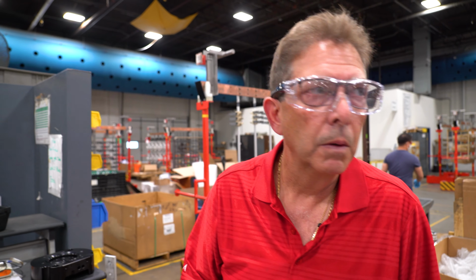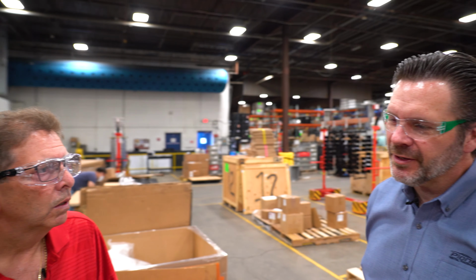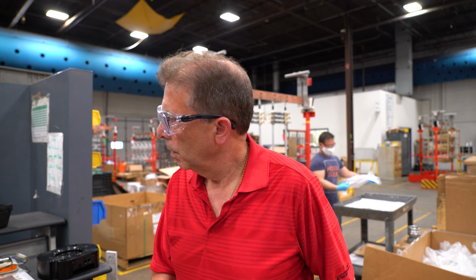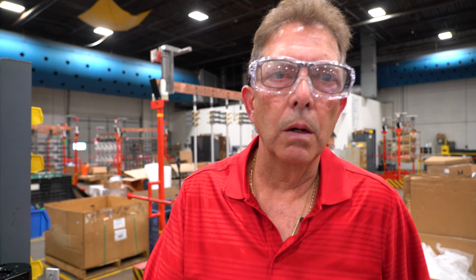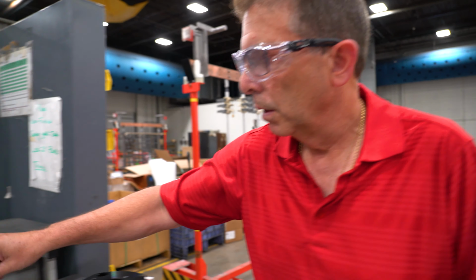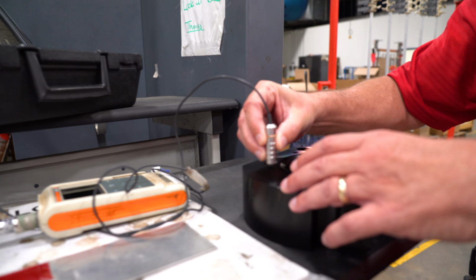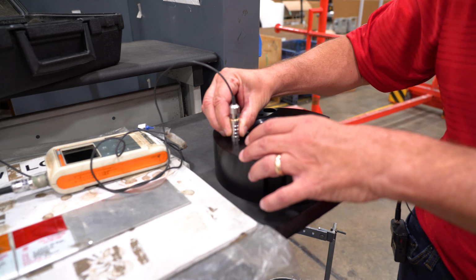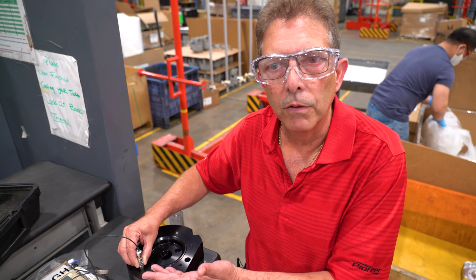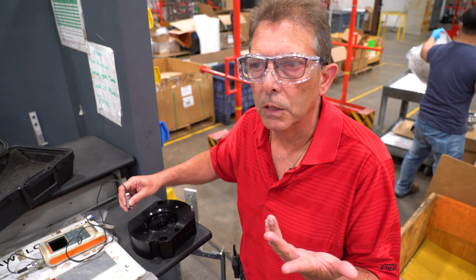So Steve, how would we specifically verify the coating thickness post running these parts? Great question, Corey. One of the things we do is we use eddy current testers. So if you want to get a shot here, here's what we do. We'll measure the coating thickness by doing this test. We take 5 readings on a part, take the average of the coating thickness, and validate it meets the specification that's required.